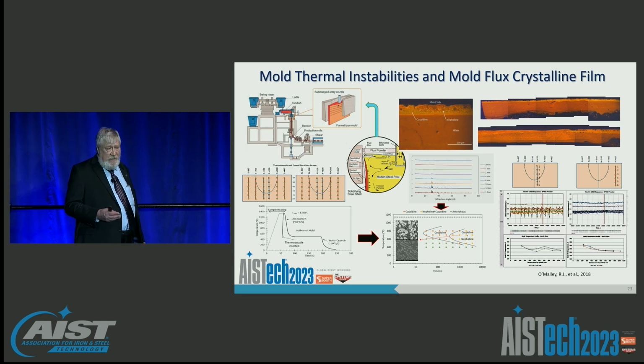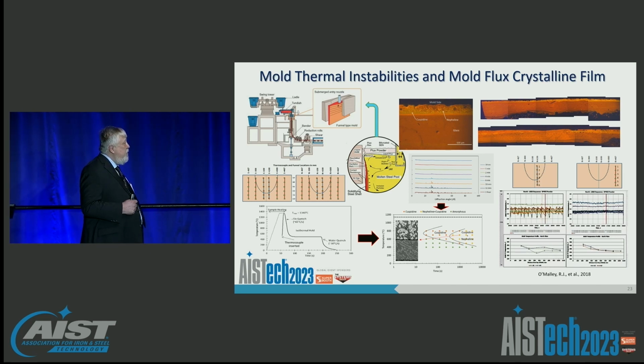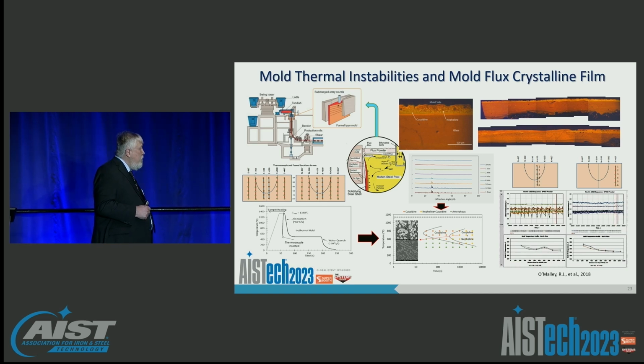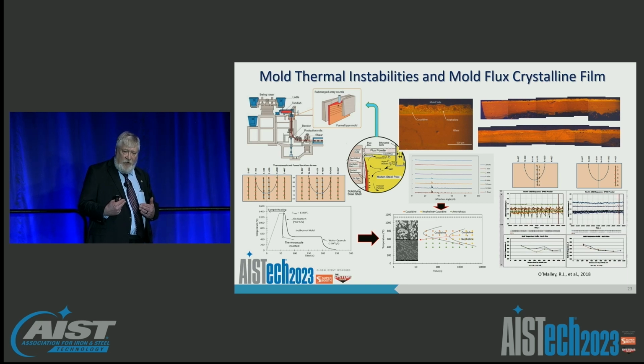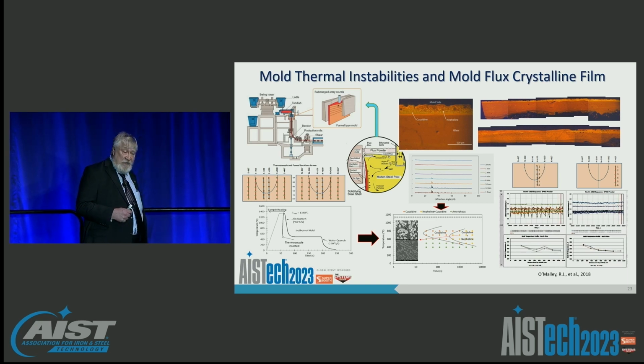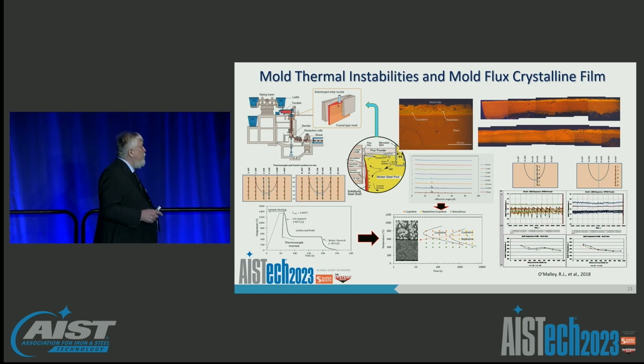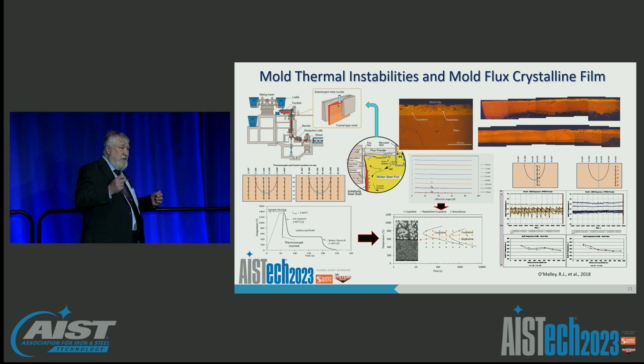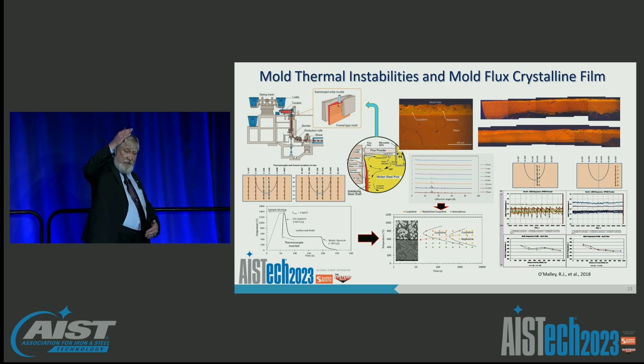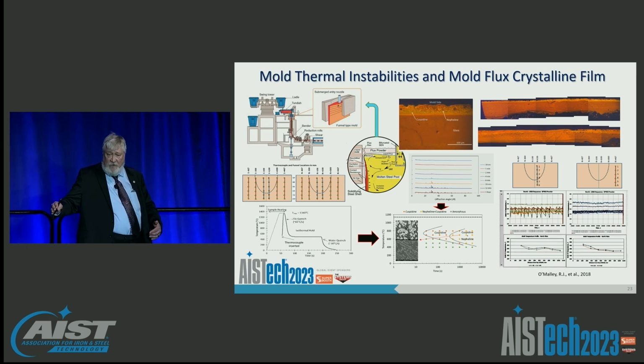What causes that instability, it turns out, is the stability of the mold flux crystalline layer. And in the upper right, I actually show in that light orange layer in that flux film what that crystalline layer looks like when it's stable. But in the lower right, you can see where when that flux film is extracted from the root area of the funnel, that film has fractured. And in fact, what we see in these sawtooth fluctuations is the extraction of that crystalline layer, the formation of an air gap, infiltration of that air gap with glass. That brings the heat removal up high, and then you can watch the slow crystallization of that layer to lower the heat removal.